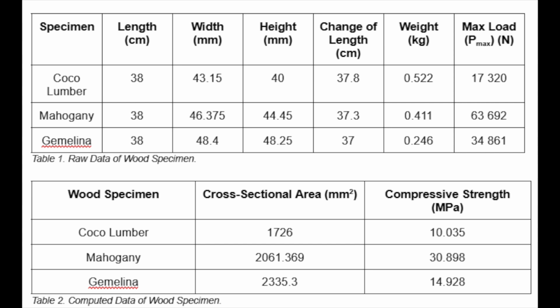Its superior performance is further emphasized by its highest maximum load at 63,692 newtons, nearly double that of Gmelina at 34,861 newtons and significantly higher than cocoa lumber at 17,320 newtons, despite having a lighter weight of 0.411 kilogram compared to cocoa lumber's 0.522 kilogram.